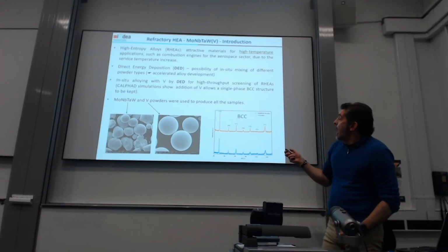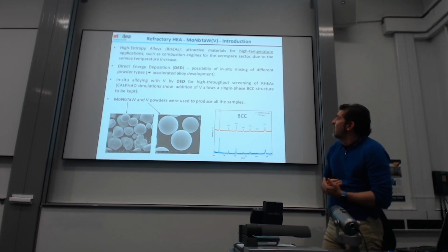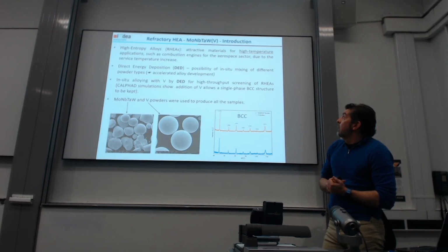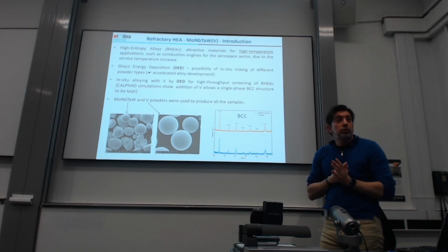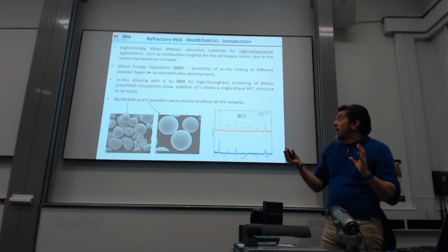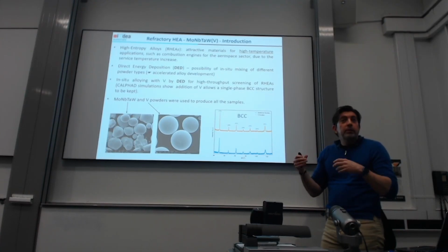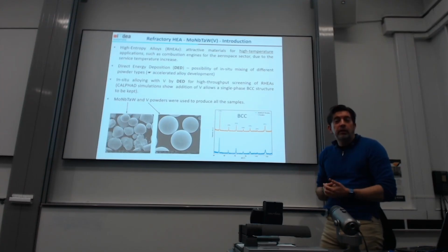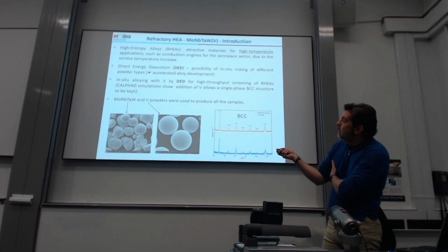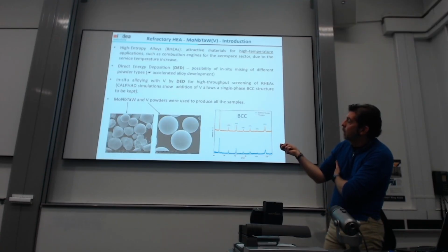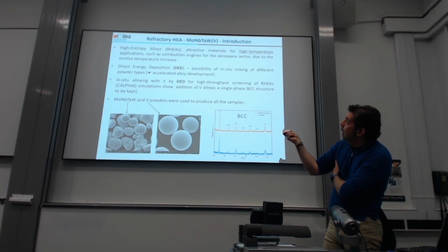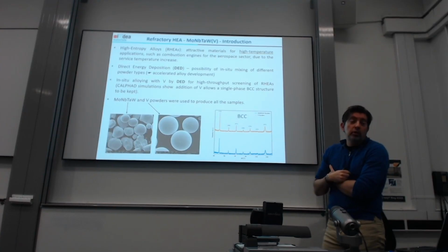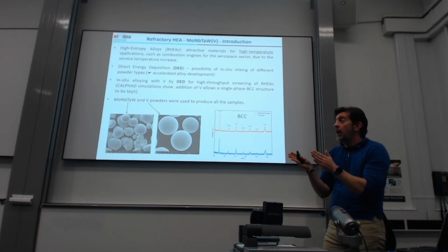They were deposited by this direct energy deposition technique, which is good because in the academic and industrial communities, they use this technique for in situ mixing, to try out different compositions in one go, because you can change the powder types and the quantity of the powder to check different compositions. And some CALPHAD simulations have shown that adding, for example, vanadium or titanium to this refractory high entropy alloy, you can keep the BCC structure. So eventually we will have the same BCC as the powders.